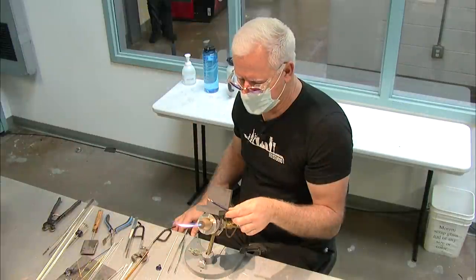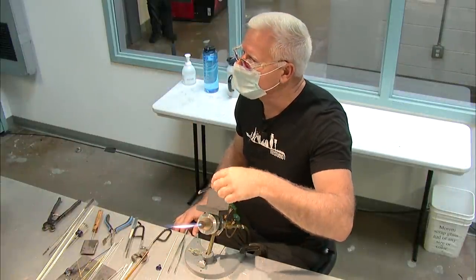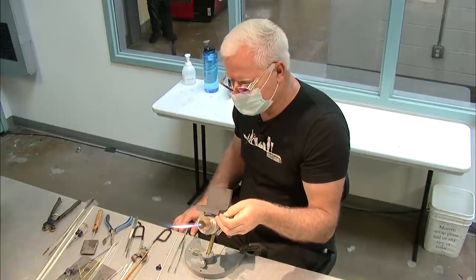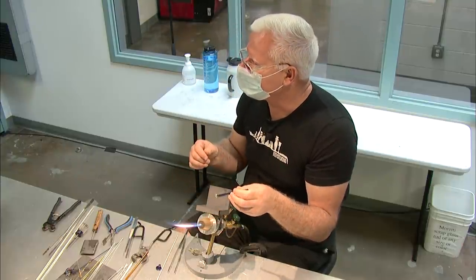But we do have to wait for the glow to come out. And so what we will get here is more of this caramel color, earthy color, sometimes gray. Not very attractive, but it does pull that color down. You don't get those attractive greens, you get grays, caramels. Now the longer you stay, the darker it'll get.